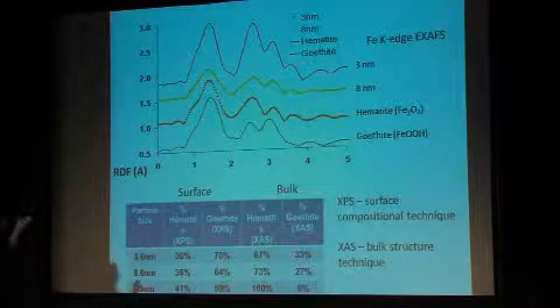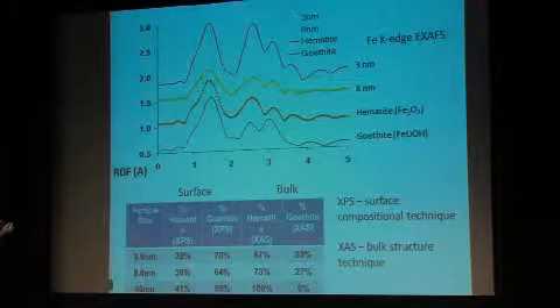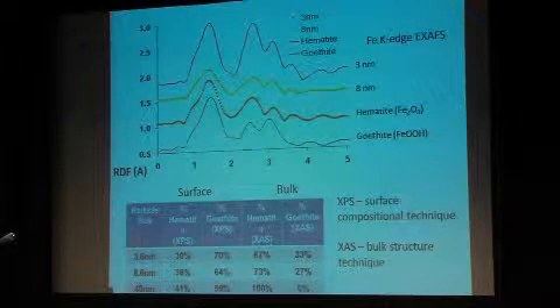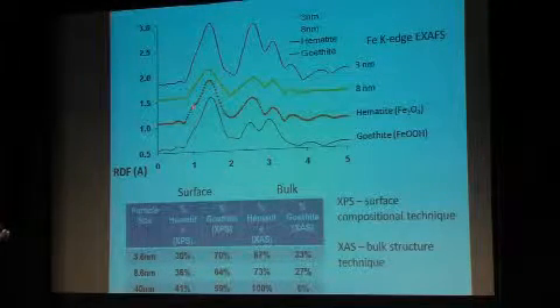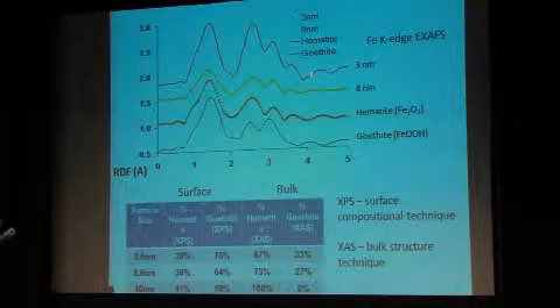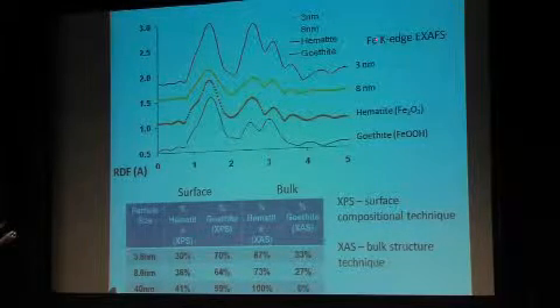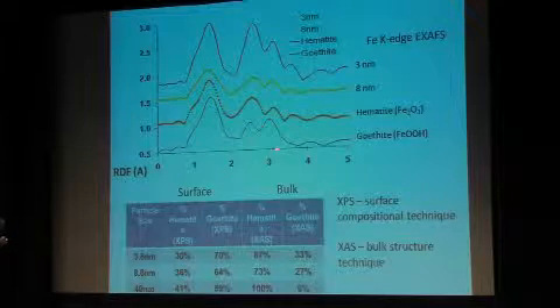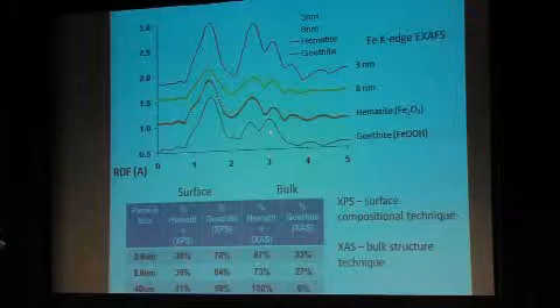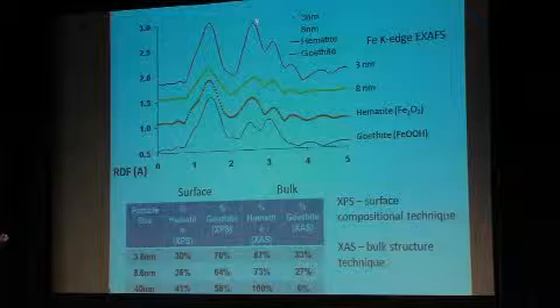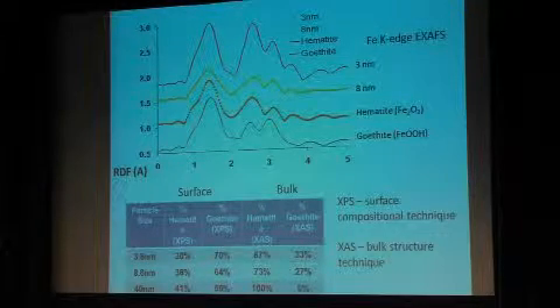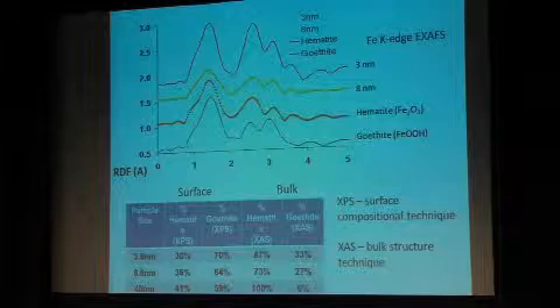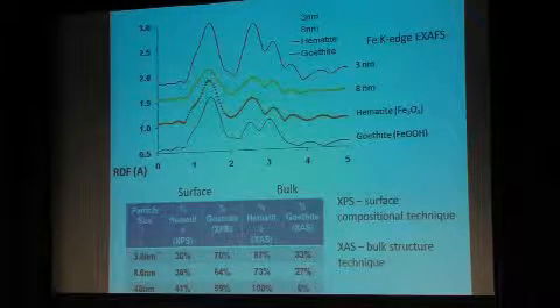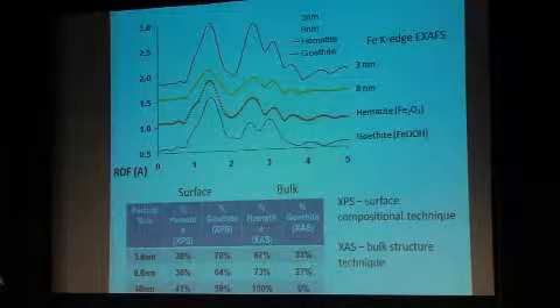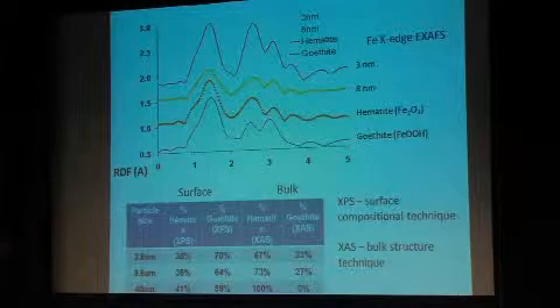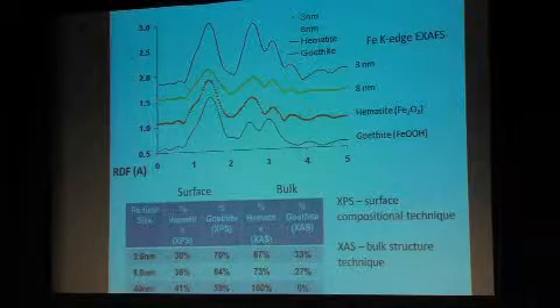What we see from the XAFS is that as we get very small, so we go from a large crystal of hematite, these are probably about 100 nanometers, to the 8 nanometer to the 3 nanometers, the structure takes on an increasingly more goethite-like character. You can see that in this area. You can see it over in here. And with X-ray photoelectron spectroscopy, which is a surface-sensitive technique, we also see a more goethite-like character. Now, it may not be exactly goethite, but the thing is it's more iron hydroxide rather than iron oxide character.